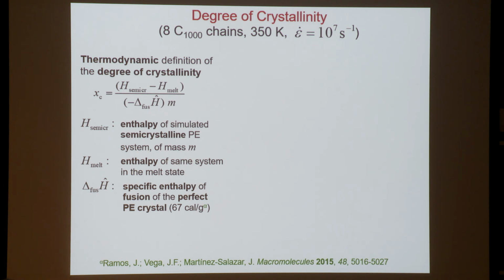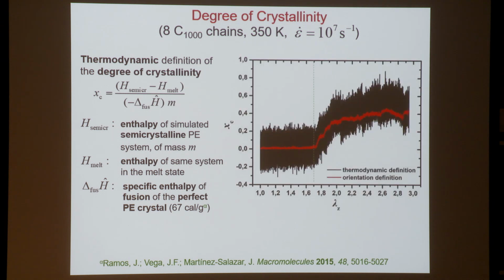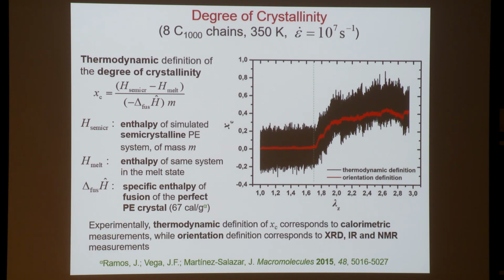One can take the enthalpy of the simulated system and subtract from it the enthalpy of an equal amount of melt, according to the molecular model used, divide by the mass, and also divide by the specific enthalpy of fusion, and that way calculate the calorimetric, so to speak, degree of crystallinity. This is shown with these very rapidly fluctuating black lines, and by and large it is consistent with a structurally calculated one, the red line. So these would be two different simulation approaches to calculating crystallinity that are sort of analogous to calorimetry and X-ray diffraction.